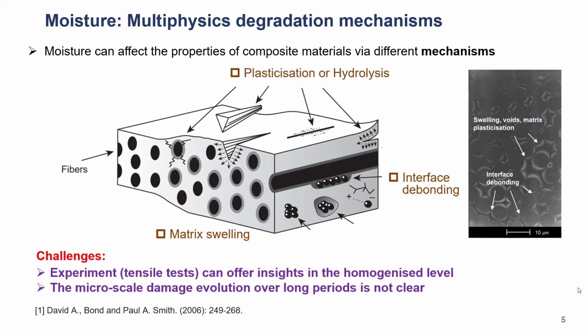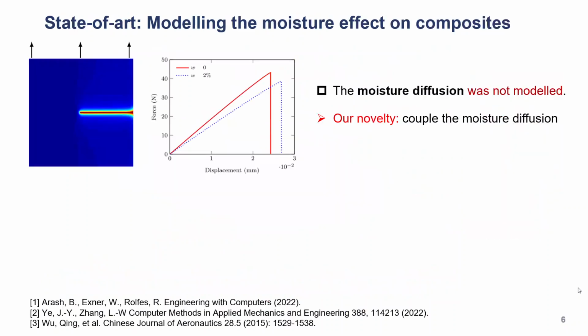So how are we going to reveal that damage? This needs a very powerful combination of experiment and computational model to help us understand the underlying mechanisms. The state-of-the-art modeling in these areas typically remains relatively unexplored. In the paper published by Arash in 2022, the moisture diffusion was not modeled. Instead, they assumed uniform distribution in the material. We will try to present a multiphysics model to incorporate the moisture diffusion.